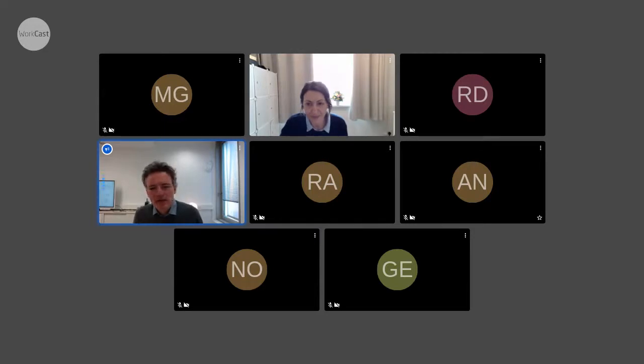In a full cell, all the alkali ions have to be supplied by the counter electrode. And if you have too high an irreversible capacity, this means that too much lithium or sodium is irreversibly trapped in your electrode and is missing for all forthcoming cycles. The only way around this is to oversize your counter electrode, and this means extra weight and extra cost. So you need to make sure that the irreversible capacity on both electrodes, not only the anode but also the cathode, is as low as possible.